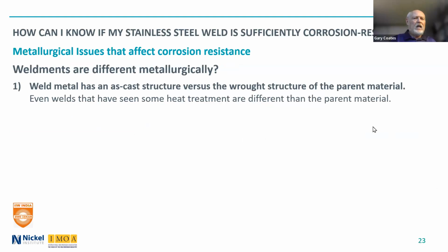So first of all, are weldments different metallurgically? And of course, the answer is yes. The weld metal has an as-cast structure versus the wrought structure of the parent material, which looks a lot different. It's been annealed. It's been worked so that the grains are completely different than the as-cast structure. And even a cast material, if you buy a cast valve or pump, that pump has been annealed afterwards. So you do have a different structure when it's annealed. Not the same as the wrought material, but a different one than the as cast.